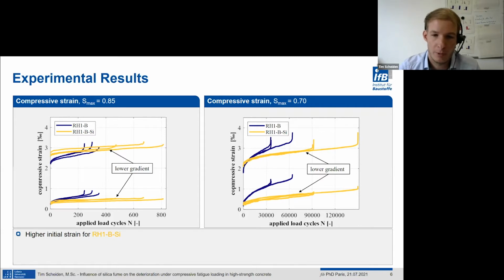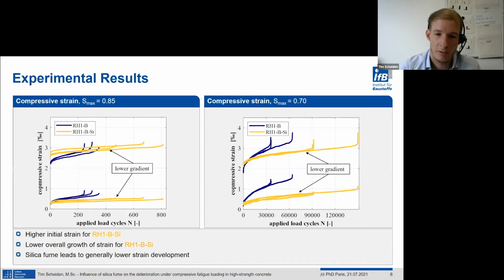On both stress levels, it becomes clear that the concrete with silica fume has a higher initial strain, which can be explained by the ratio of the applied stress in combination with the ratio of the modulus of elasticity. Also, the concrete with silica fume has a lower overall growth of strain due to the lower gradients, meaning lower strain increase per load cycle in the second phase. This behavior applies for both stress levels, meaning that the addition of silica fume leads generally to a lower strain development.